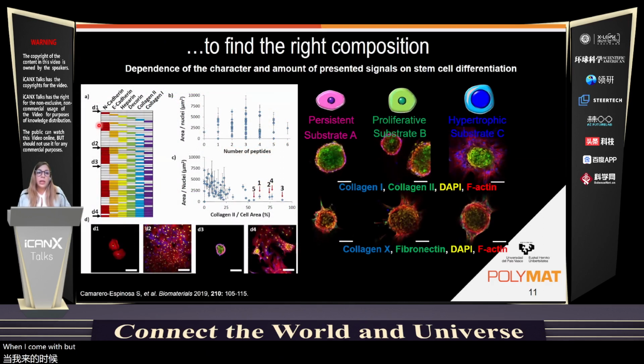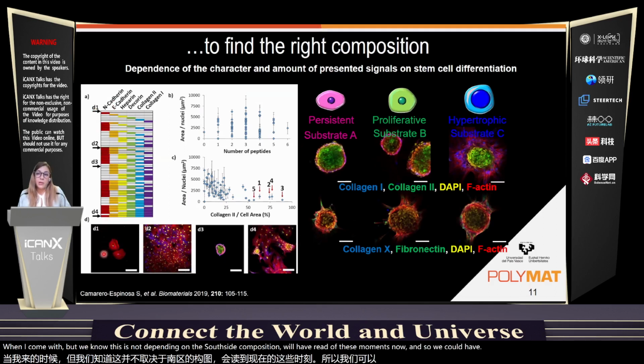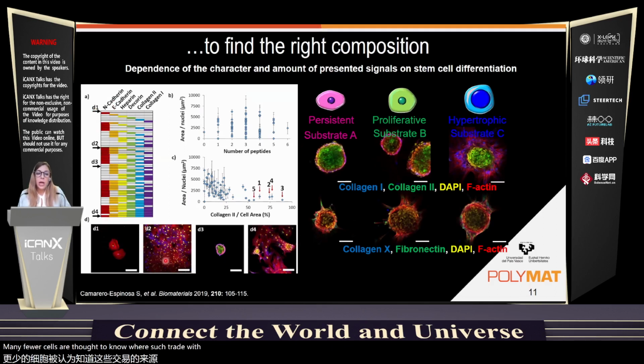What we notice is that depending on the substrate composition, we will have very different scenarios. So we could have very few cells attached on our substrate. We could have the formation of monolayers, the formation of aggregates, and intermediate states.